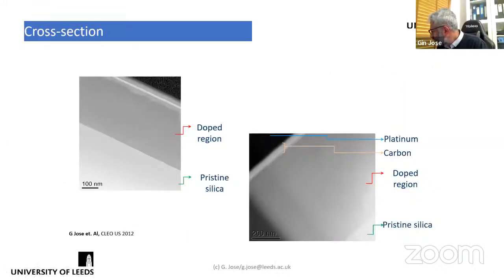So we can look in much more detail into the glass. You can see the doped layer. You can control the thickness of the layer by controlling the laser parameters. That's a cross section shown at a higher magnification.